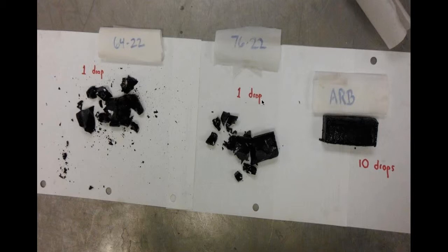10 drops of the hammer on that asphalt rubber absolutely blew me away. I realized then the value, especially in the state of Pennsylvania, when we look at thermal cracking, the freeze-thaw cycling we have. Anybody who's looked at pavements, like, of course, I've looked at pavements too much, but thermal cracking happens no matter what kind of pavement you have. Of course, concrete cracks much quicker.